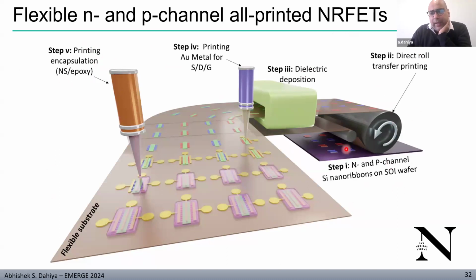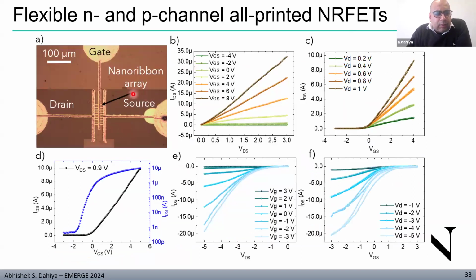So in step one, we have used our roll approach to print nanoribbons. Then it goes into the dielectric deposition, which is again at room temperature, silicon nitride. And then we bring in our drop-on-demand printer for the source, drain, gate electrode, and encapsulation. This is a typical device, how it looks. So we have these nanoribbons, the gate electrode and source and drain printed, and typical electrical characterization performed, output scan, and some transfer scan for both P and N type devices.